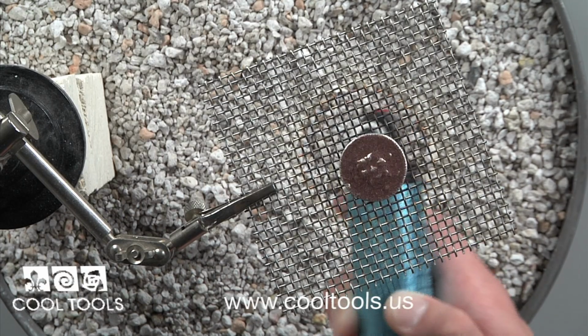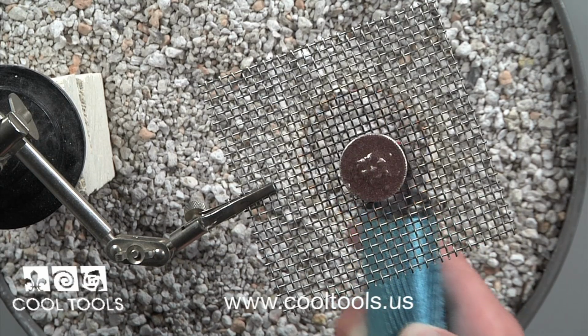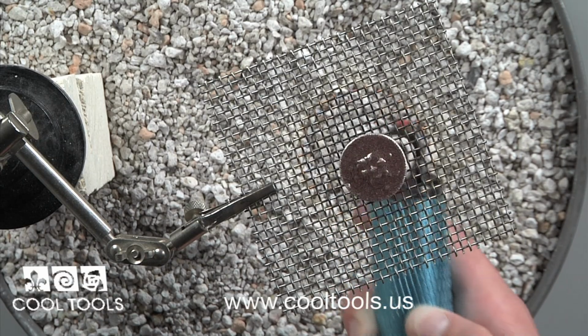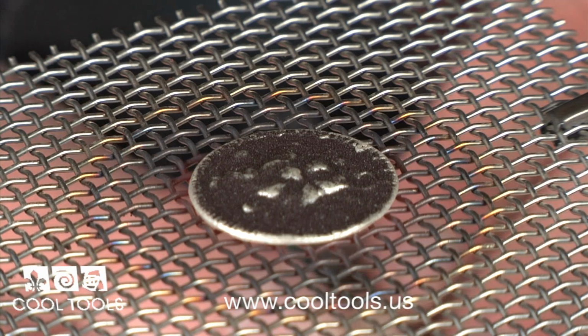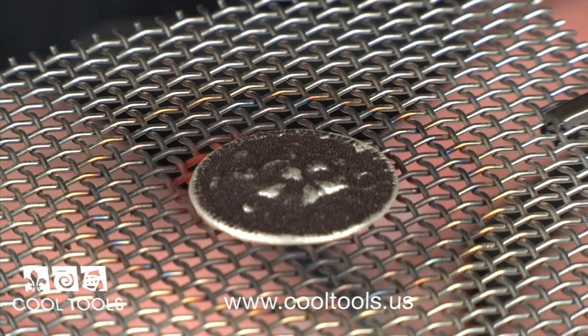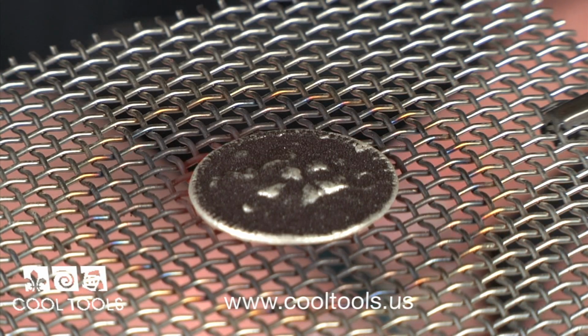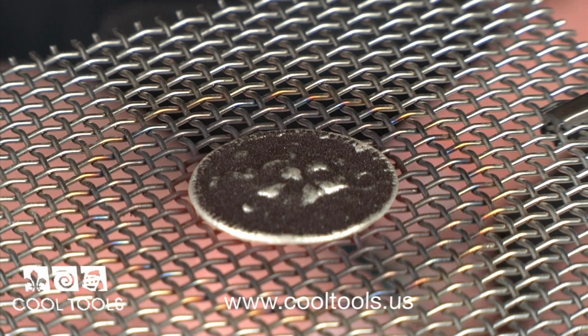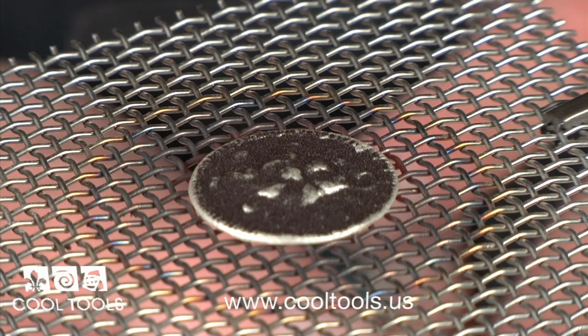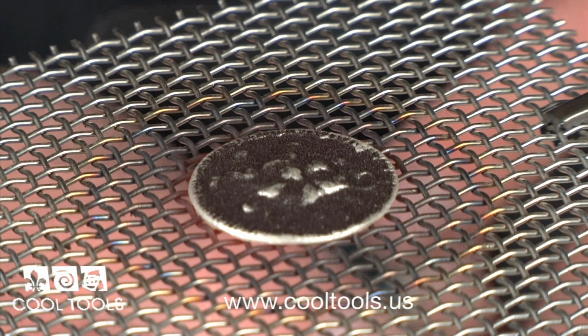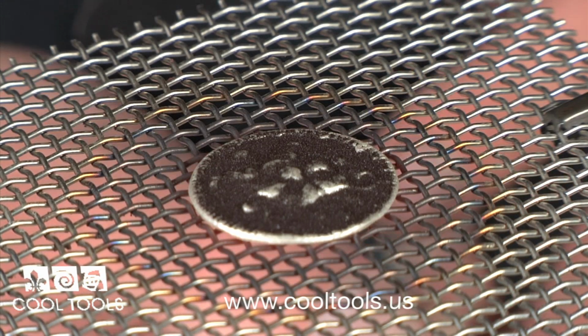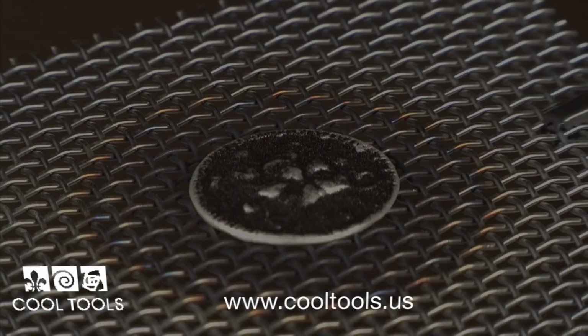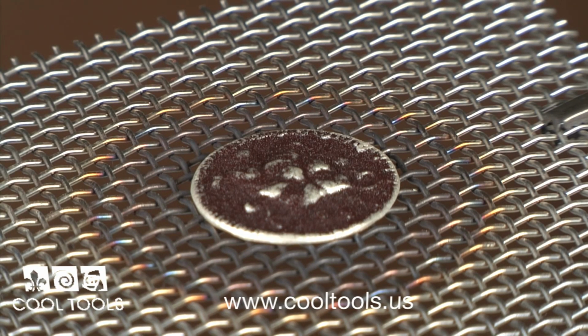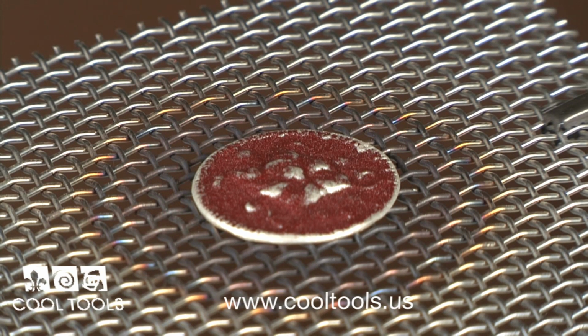You'll need to watch two things: the fusing of the enamel and the color of your metal. Do not allow your metal to get any brighter than a pale pink. If it starts to turn orange, back the torch off. When your enamel reaches a smooth, glossy finish, let it cool. As seen here in this 2-minute time-lapse video, the original red hue returns.